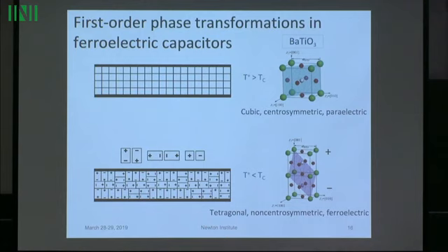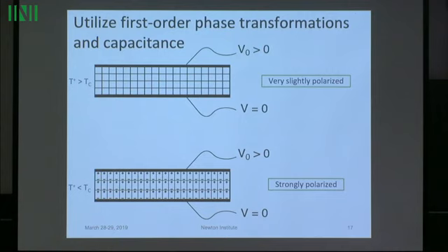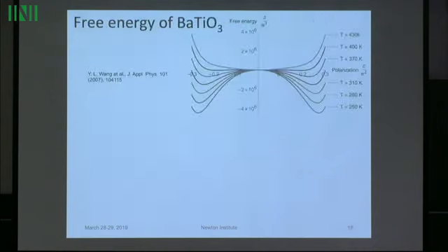You might draw a picture like this. And the point about this is that in barium titanate, the high temperature phase is non-ferroelectric, it's paraelectric. So there's no strong polarization exhibited in that phase. If you phase transform and you have a voltage on the plates, it will tend to phase transform to the variant that's pictured here, which has its polarization in the vertical direction, and this will be very strongly polarized. So this will have the tendency, as you can see from all these plus charges, to attract a lot of charge. Okay, so that's the effect we're going to use.